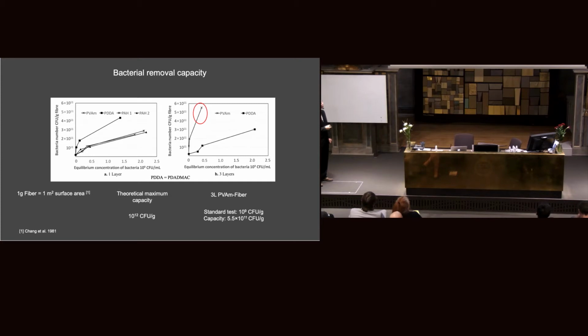Therefore, we increased the bacterial solution concentration and decreased the amount of modified fiber used. We reached a capacity of the 3-layer modified PVAm-Fiber sample of 5.5 times 10^11 cell units, much closer to the maximum capacity.